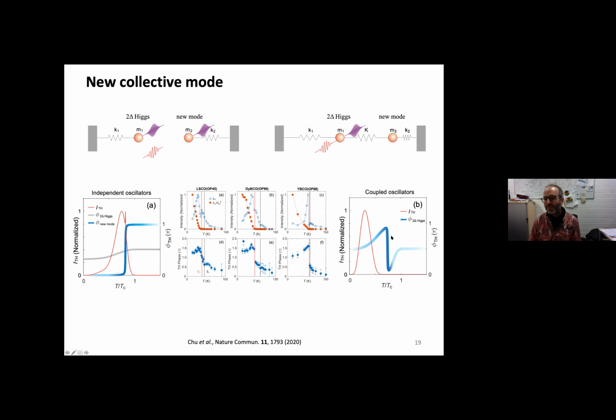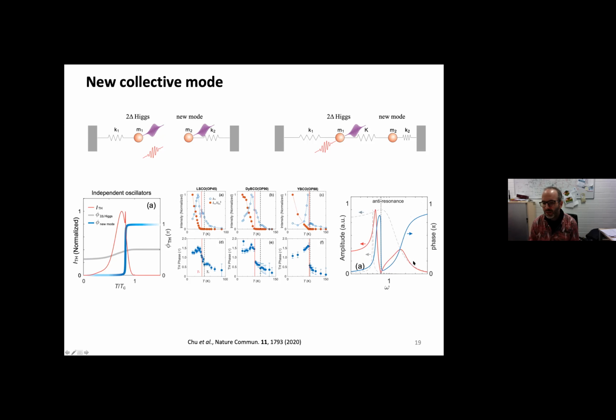And of course, this looks maybe a little bit strange to you if you work with oscillators or with phonons in your system, because keep in mind here we see intensity and phase over temperature in the system. If you go back to the model behind that has the oscillators, you really see this is a model that has two oscillators. One broad oscillator of the Higgs mode, dashed here in the background, and a very sharp new mode that is here inside the gap. And then really the amplitude shows two peaks with an anti-resonance, and that is exactly where the phase here in blue shows this drop around this frequency.